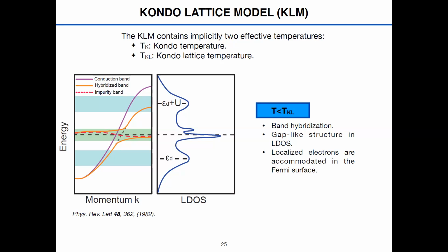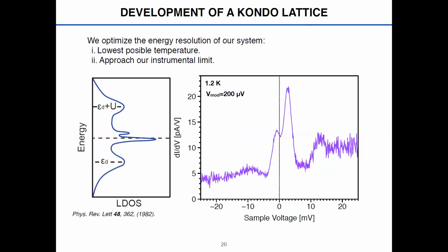More important for us is that because the flat impurity band has hybridized with the conduction bands, you now have a gap here, and therefore what you expect to find in your local density of states is that a gap-like structure appears superposed with your Kondo resonance. So we want to try and measure this, and to do this, we are going to try and optimize our resolution. And we can do this in two ways.